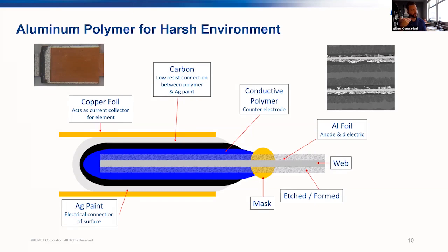So you have a core aluminum anode, and on that is etched a very, very high surface area, almost porous nature of it. And you grow an oxide dielectric on it, in this case, obviously aluminum oxide. And then you apply a conductive polymer cathode, and that's one single aluminum polymer element. And then you start stacking those, and you get a high degree of capacitance. So that's in a nutshell what aluminum polymer is.